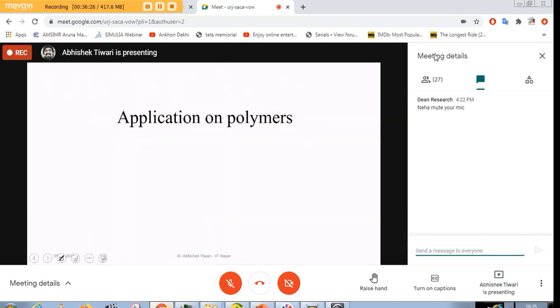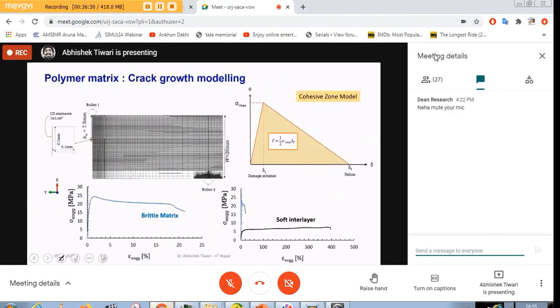Using that, we applied this concept in polymers, and in the polymers we had the matrix which was a brittle polymer. In this plot it doesn't look that brittle, but if you compare with the material which we used as interlayer, then you see how brittle it is. So this material we use as the matrix, and we put a very thin interlayer of the soft material, and before doing the experiment we model it.